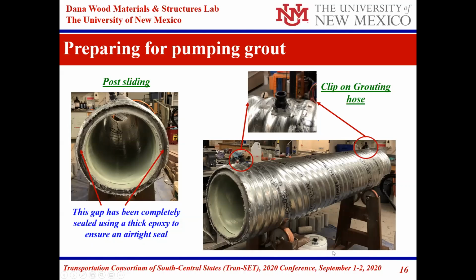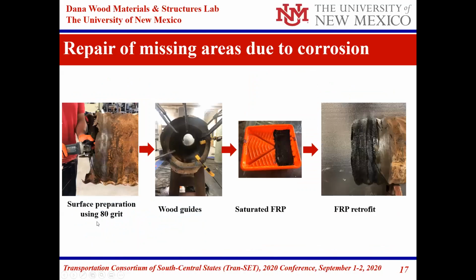This is basically some areas in the pipe, as you can see for the corroded one, that was completely lost or cracked to failure. So in this case, similar to what we do here, you will have to repair it using some saturated FRP material. And that's what we did for the case of the corroded pipe.